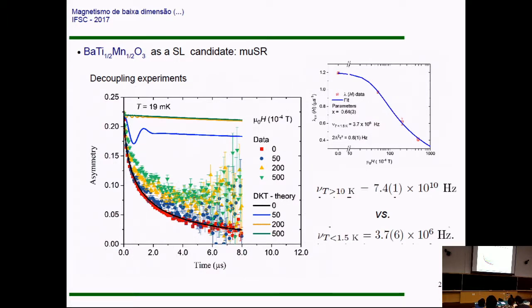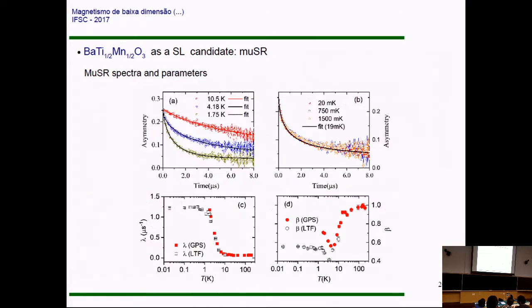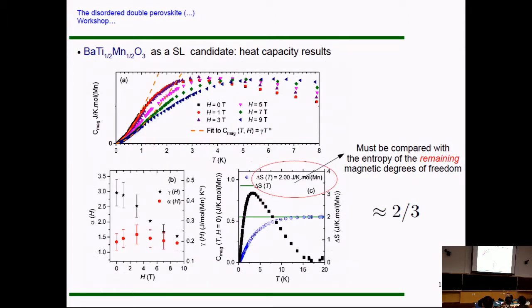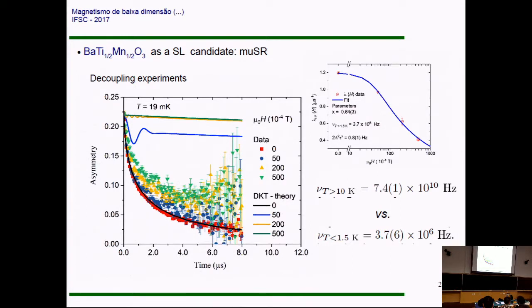So we have evidence that we still have dynamic magnetism down to 19 millikelvin, but this dynamic magnetism comes from a steep increase of this relaxation rate here. If I extract from my data the frequency of the fluctuating fields, we see that at high temperature it extends to about 7.4 times 10 to the 10 hertz, and here at low temperature, which we extract from this fit, it's about 10 to the 6.